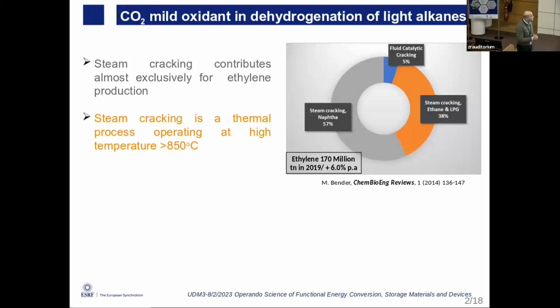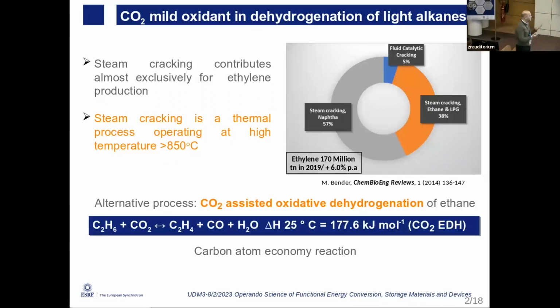So an idea is then to use the gas shale revolution, which boosted the production of combustible gases like ethane and methane as well, to dehydrogenate the ethane directly. And of course, you can do this with oxygen, but oxygen is too strong, so there is over-oxidation that is tough to control. So the role of the CO2 is that it acts as a mild oxidant. And according to the reaction reported here, it's a good one because it's at a lower temperature. It's also a carbon atom economy reaction because it exploits all the carbon atoms. And this is an alternative process to steam cracking.